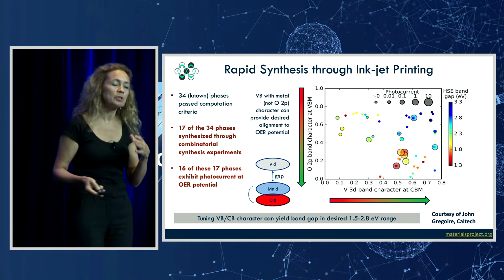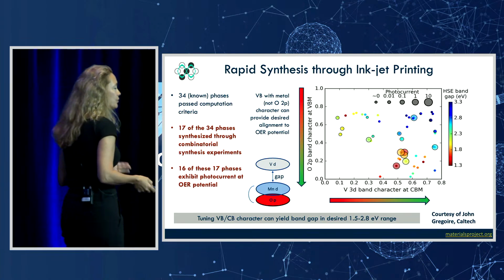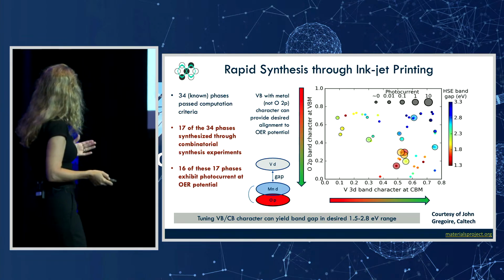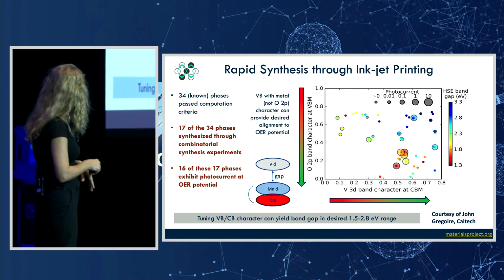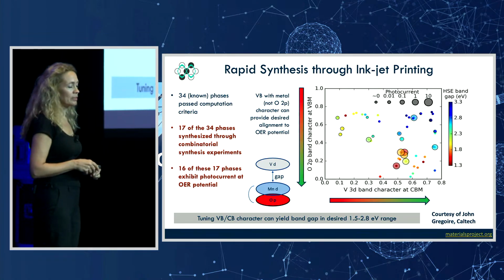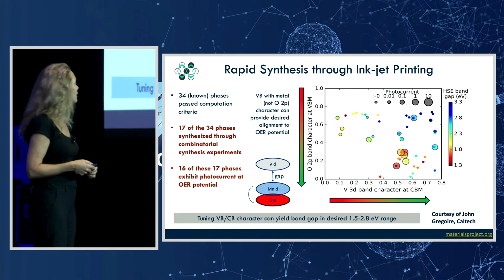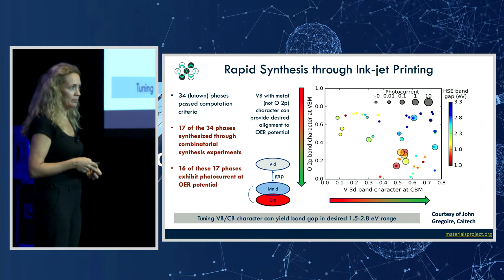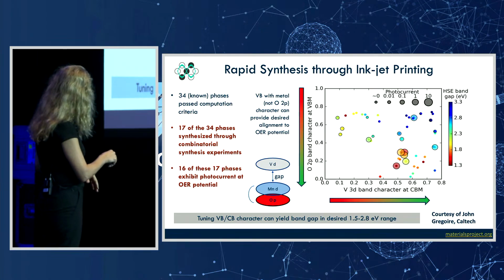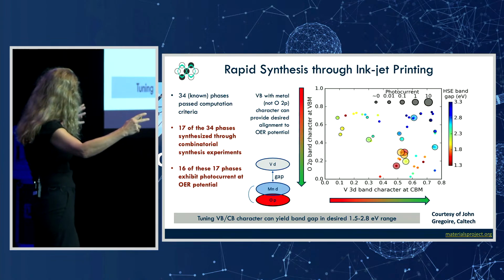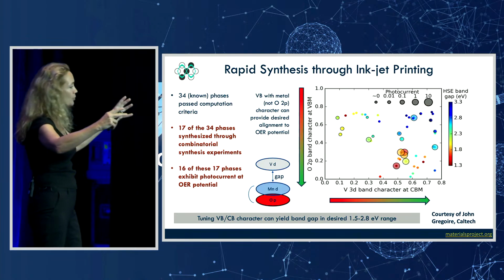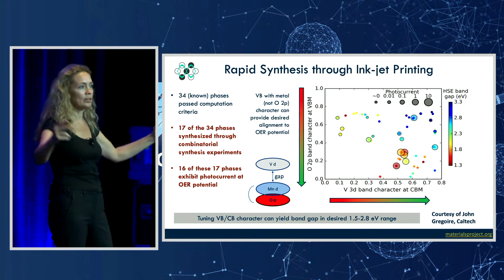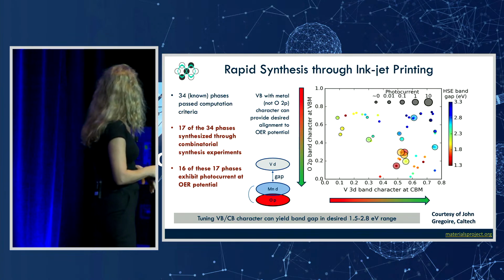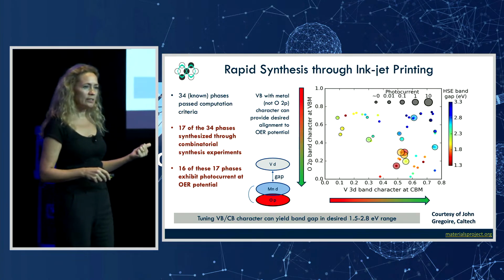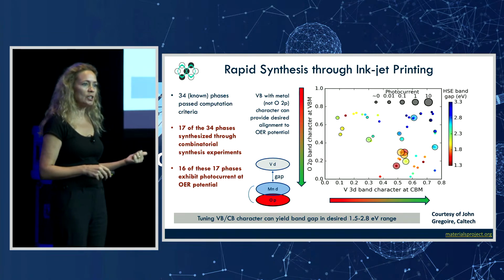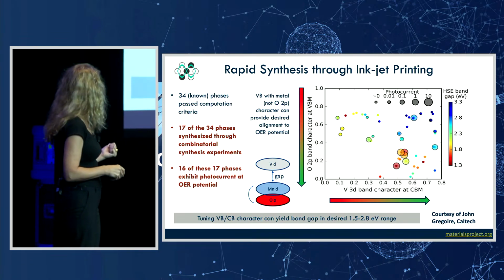And then he tested them directly for photocatalytic activity. And 16 out of the ones he was able to make actually showed activity of varying degrees. You can see here that the radius of the ring tells you about the photocurrent, so the bigger the circle, the better the material. This is pretty good, right? 16 out of 17 in terms of hit rate. Yes, he wasn't able to make 34, he was able to make 17 of them.